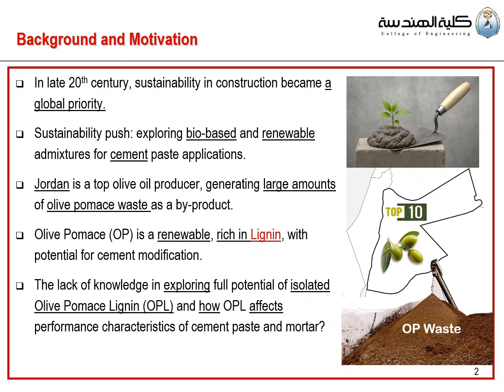Scanning the literature and state of the art, we found that exploring the full potential of isolating the olive pomace lignin is needed. I will emphasize the isolated lignin from this agricultural waste, because if you read a lot of the literature, you will find that the use of olive pomace in cement modification is not new, but isolating lignin is a novel use to test and see its effect on the performance characteristics, especially in cement paste and mortar.